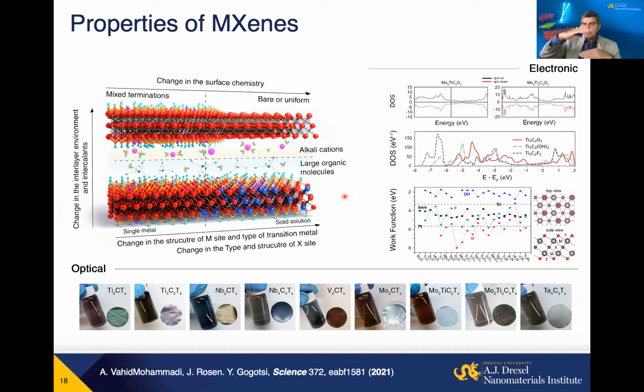And you can also consider, depending on surface termination, you pull different numbers of electrons from the surface. For example, chlorine will take 1 electron, but oxygen will pull 2 electrons from each layer here. So we get this surface chemistry, and this is actually density of states here showing tunable electronic structure. We reported recently an antiferromagnetic transition at about 35 Kelvin in chromium titanium carbide here. There have been predictions of superconductivity in a number of materials here. There are effects that we are trying to understand, like hysteresis of conductivity due to surface groups or intercalants here.